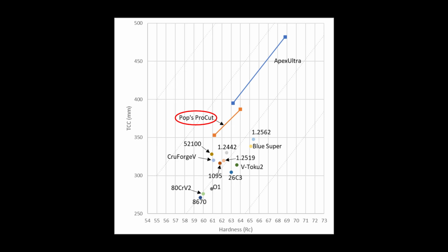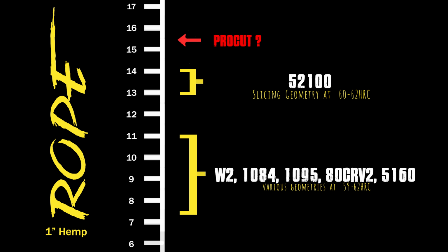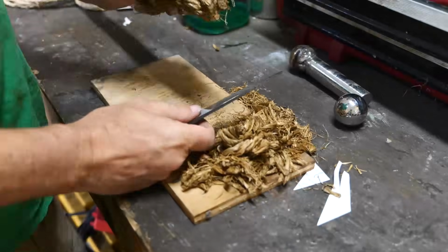Larrin's also done some CATRA edge retention testing, and ProCut outperforms 52100 steel by 8 to 10% and 1095 by about 20%, which is pretty amazing if that's true. So one has to decide what CATRA testing means to them, as we don't go around cutting CATRA cards in the real world, but 52100 is such a terrific performing steel, I'm excited to see if ProCut can perform even better. Here's the first knife I made with ProCut.